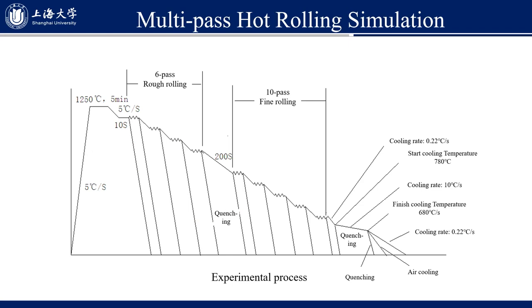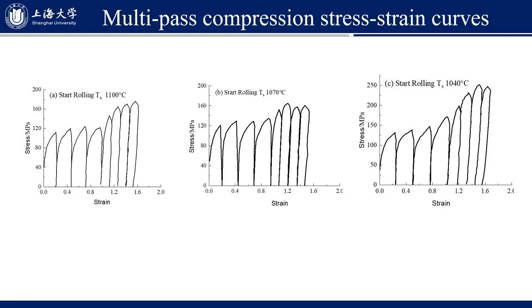Then let's go to the multi-pass hot rolling simulation, simulating the 6-pass rough rolling and 10-pass finish rolling. After hot rolling, the steel will be controlled-cooled to room temperature. Firstly, with a slow cooling rate, and the start cooling temperature is 780 degrees C. Then the cooling rate is controlled at 10 degrees per second, and the finish cooling temperature is set to 680 degrees C. After that, slow cooling rate air cooling and very fast cooling rate are conducted on different samples to room temperature. This is the multi-pass compression test stress-strain curves of the steel after multi-pass compression.